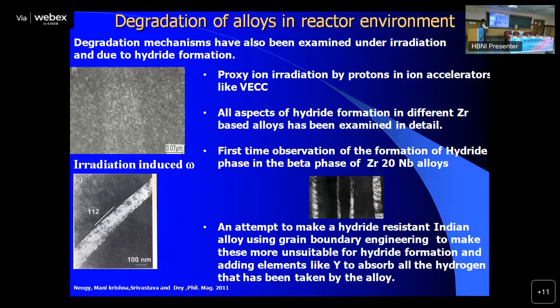So this is neutron irradiation. This I told you is a shock formed material where the omega phase is formed, not desirable. This can happen during an accident scenario. When there is shock pressure developed, then the material will become further brittle because the omega phase is formed.